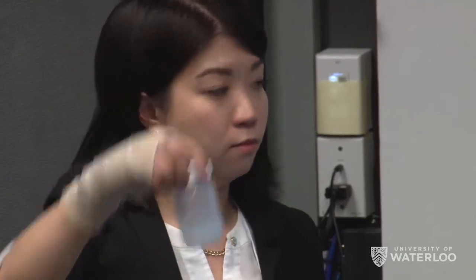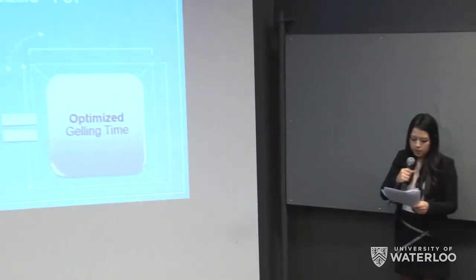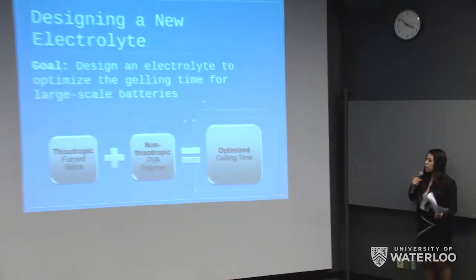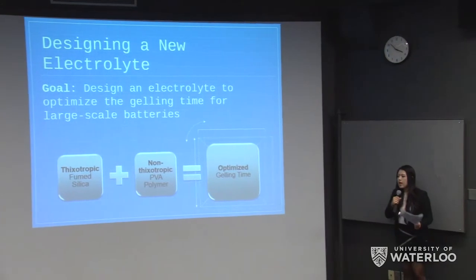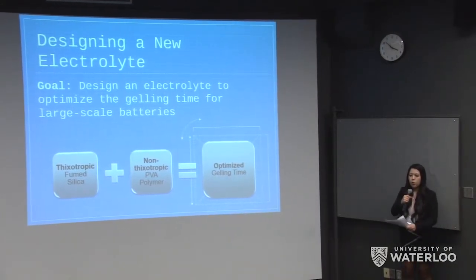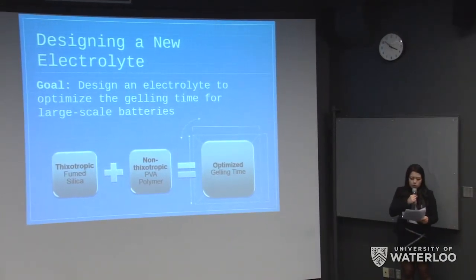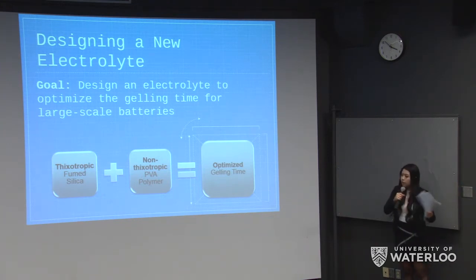Unfortunately, it's not gelled because we kept showing it in demonstrations, so we brought it at a time where it didn't have full time to gel yet, but if you leave it, then once it gels, even if you invert the container, it won't move at all. So the gelling time of just a pure thixotropic solution is not long enough for it to be able to wet a separator, and so we decided to modify the gelling time by combining that with a non-thixotropic polymer.